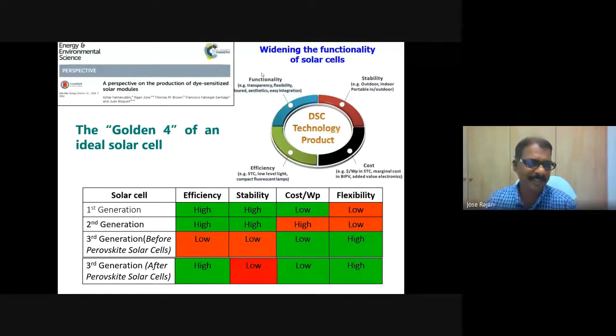For example, we can divide the 3rd generation solar cells into before and after perovskite solar cells. Before perovskite solar cells, there were dye-sensitized solar cells and organic or bulk heterojunction polymeric solar cells. Their efficiency is poor, stability is poor. Both efficiency and stability were low. But when it comes to perovskite solar cells, we could eliminate one of the drawbacks. Efficiency is pretty high, and can be as high as that of silicon solar cells.